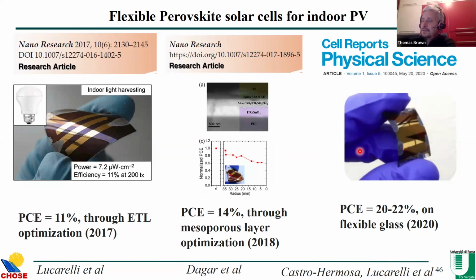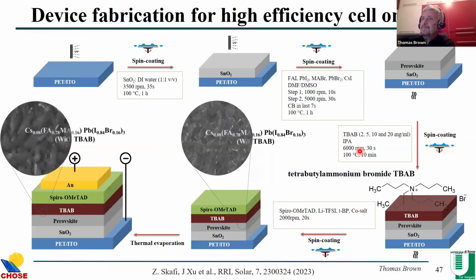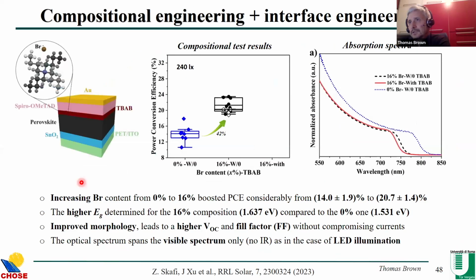We also use flexible glass. And recently, we use PET, which is the main plastic substrate for organic electronics. And we deposited SnO2, the perovskite. Then we processed it with a molecule called tetrabutylammonium bromide, TBAB. Then deposited the hole transport layer, spiro-OMeTAD, and the metallic contact on top.